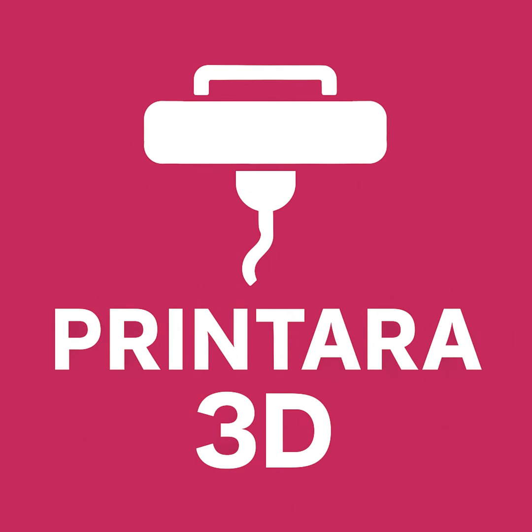It's a long way to go. It is. Now imagine trying to push a wet noodle through a drinking straw. Oh, that is a great analogy. Right. The pushing force applied by those gears transfers onto that highly elastic 75A TPU. But because the material is soft, it does not just move forward. It compresses. It buckles. Yes, it buckles and expands outward against the inner walls of the PTFE tube. The friction inside that tube increases exponentially the harder you push. Until it just binds up entirely. Yep. Or it just squirts out the side of the gears at the motor and wraps around the driving axle like a bird's nest. Which is just the worst to clean up.